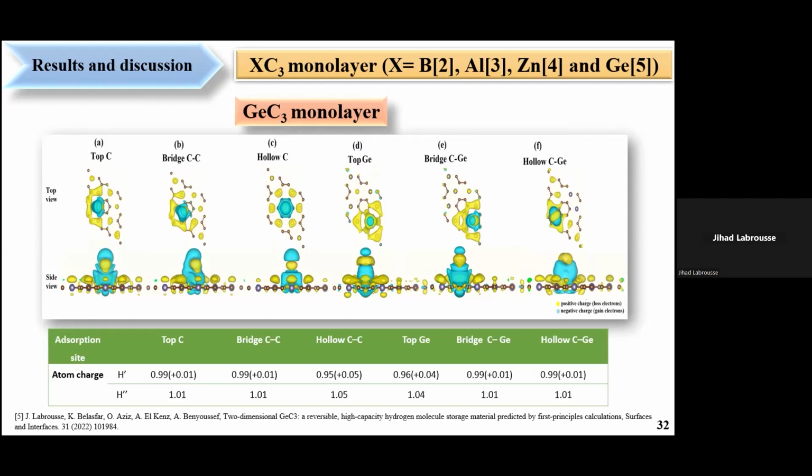We observed that during the adsorption of the hydrogen molecule at the surface, the hydrogen is polarized with an electrical field on the surface. Therefore, between the hydrogen molecule and our layer, there exists a dipolar interaction, which means that our material and the molecule are connected by van der Waals interactions, which is physisorption. And this exchange of electrons was confirmed by Bader charge analysis.